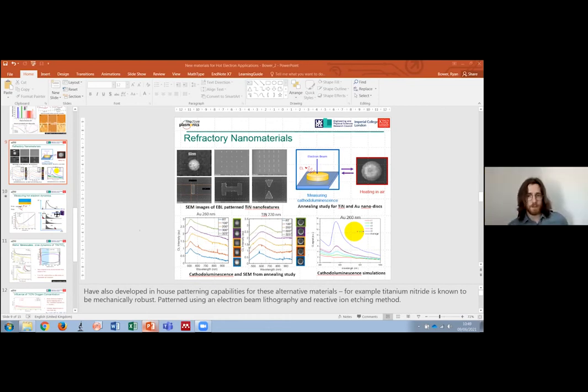So we do see some evolution of the higher order modes with increased disk diameter, which might be explaining that there. But with titanium nitride, we have poorer emission, so it's lossier. So we have these generally lower intensity peaks and broader peaks, which might be why we see spectral features in gold that we don't necessarily see in the titanium nitride.